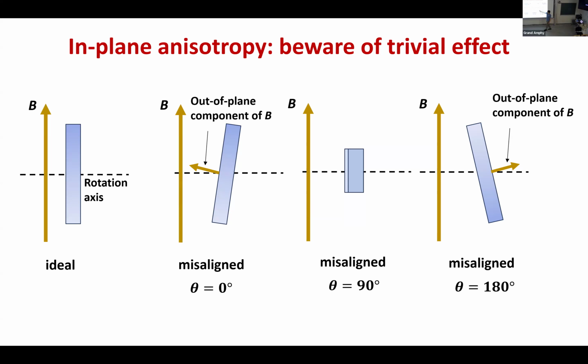Suppose now I start to rotate, like my pointer here, I rotate this to 90 degrees. This is still fine because now your sample plane is parallel to the magnetic field. If I keep rotating to the other side, then the out-of-plane component changes direction and appears again. So if I rotate the full circle, the out-of-plane component shows up twice. That can, in principle, give you the twofold symmetry.